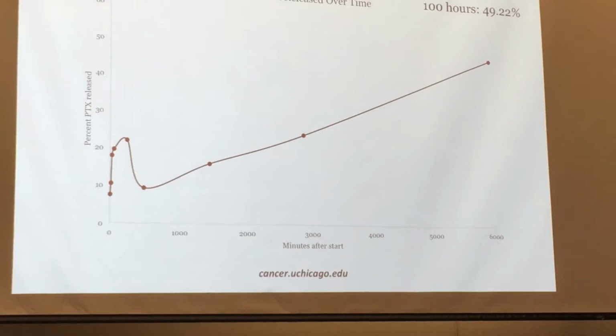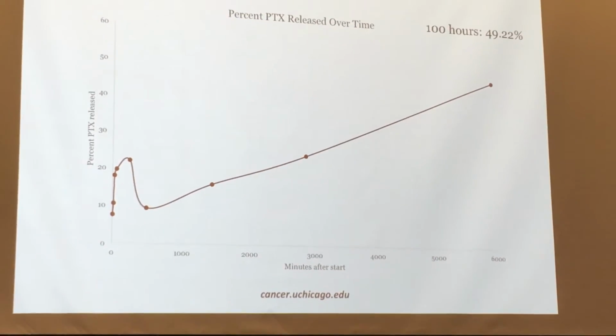The increase at the beginning is probably the UV-vis machine picking up the absorbance of the other lipids that were released into the solution, which then probably crashed out of solution, and the linear release is most likely the paclitaxel.